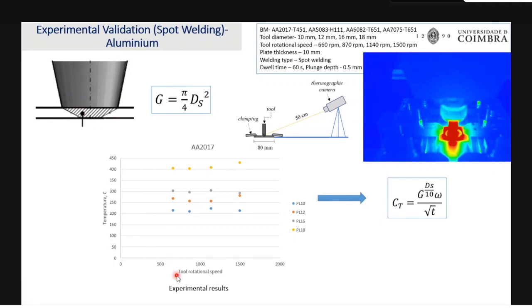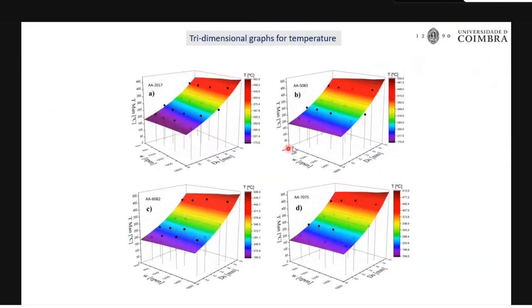Here you can see that as the tool rotation speed increases, the temperature is not increasing so much, whereas as the shoulder diameter increases, it is increasing a lot. So in this way, in order to give more weightage to the tool dimension, I introduced this term. Here also it is giving good fitting. Sorry, the surface plot is the predicted value, and the dotted plots are the experimental values. So it is perfectly matching with the different grades of aluminum.